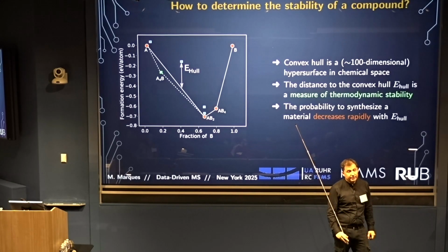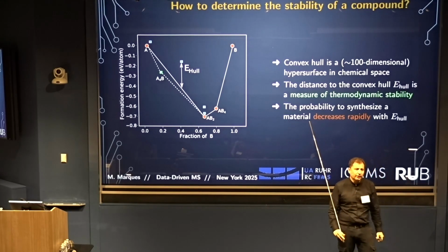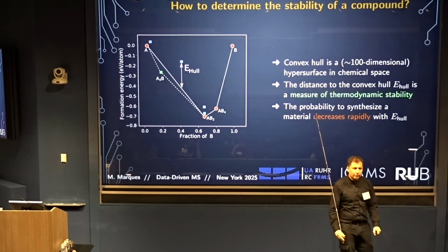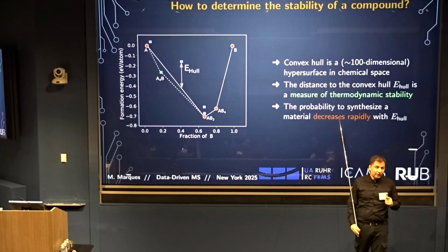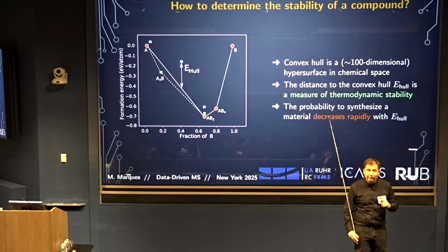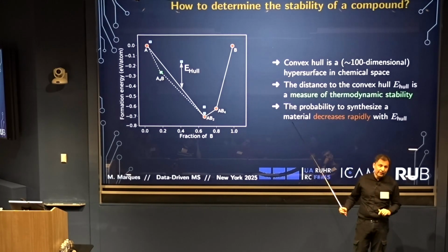So this is the number you have to have: 50, 70 meV per atom, and most of the error is not in intermetallics or sulfides, it's in oxides and fluorides. But there is the other side of the coin. The experimental formation energies don't have a very small error, so it's also very hard to know what our error is.